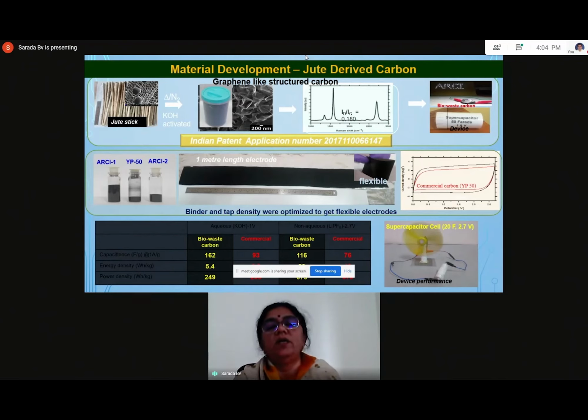And you can see over here from the very small D band and also large intensity of the G band, and the 2D band almost half the size of the G band, showing that there are very well ordered few-layer graphene structures obtained from the activated carbon that is processed from the waste jute stick. And this process is upscaled by him along with our other group members, and you can see a long sheet of this flexible carbon substrate.